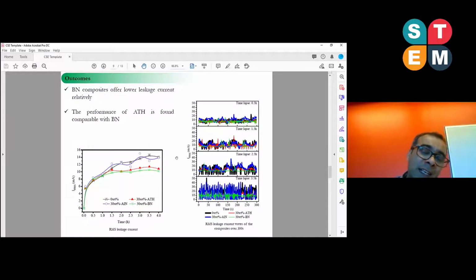So here's the leakage current. The leakage current is directly correlated with the tracking and erosion, because leakage current creates different hotspots on the insulation, and once the temperature increases on the hotspot during the dry band arcing, that dry band arcing can easily deteriorate the insulation and start electrical tracking. So we have to continuously measure the leakage current on the surface of the insulator. We measured the instantaneous current over a 5-minute period, around 300 seconds, and then calculated the RMS current. So here we have a look.